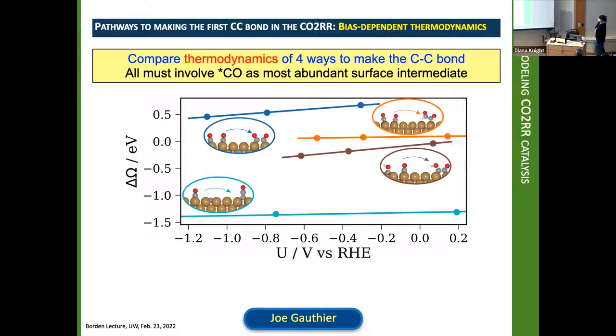On the other hand, the least favorable, up the top in dark blue, is the recombination of two CO molecules, which gradually becomes less unfavorable as you apply bias towards the negative. And in between are the CHO and COH pathways recombining with CO. But as we've seen before, kinetics often dictates what happens, not thermodynamics.